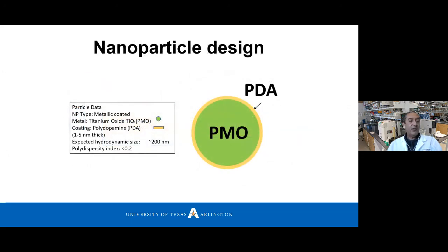So our nanoparticle design includes a core of a photocatalytic metal oxide, which is the titanium oxide, and the coating is going to be polydopamine. The purpose of the coating is to make the titanium oxide able to form reactive oxygen species under visible light irradiation, which is the more innovative part of our design. Can you go ahead, please?